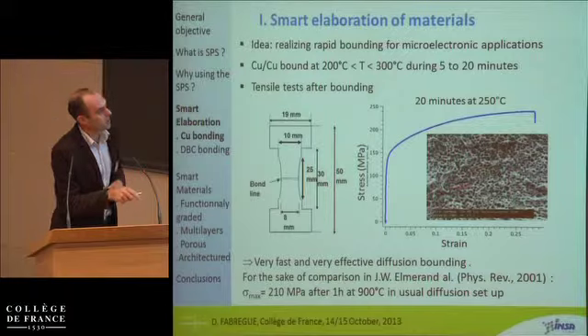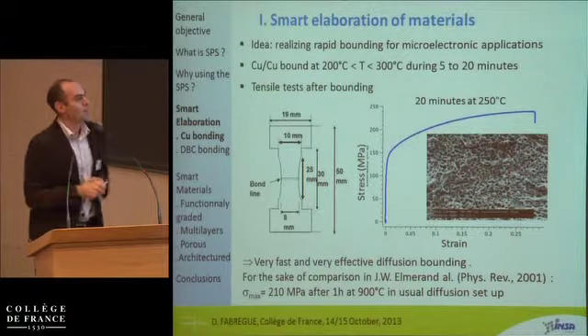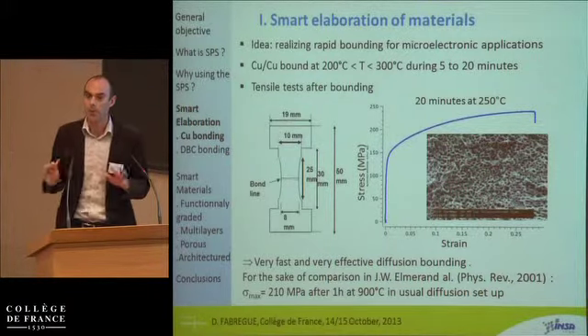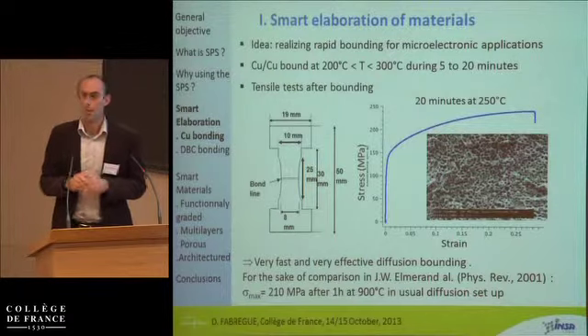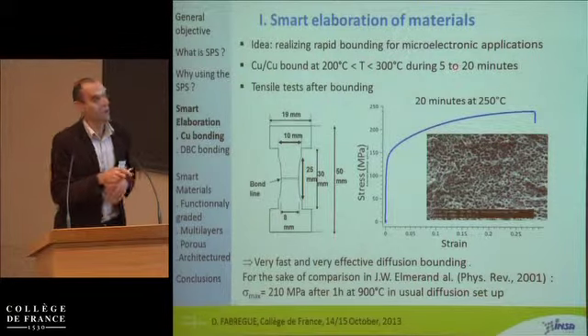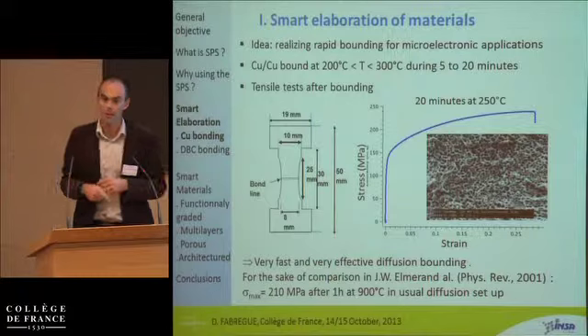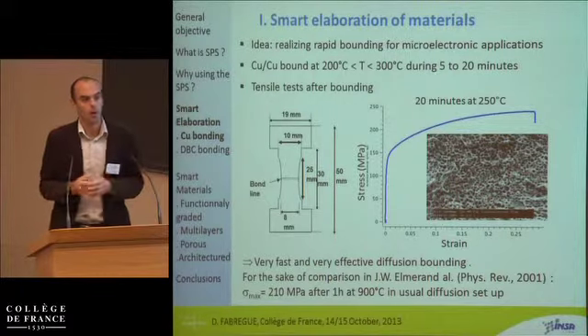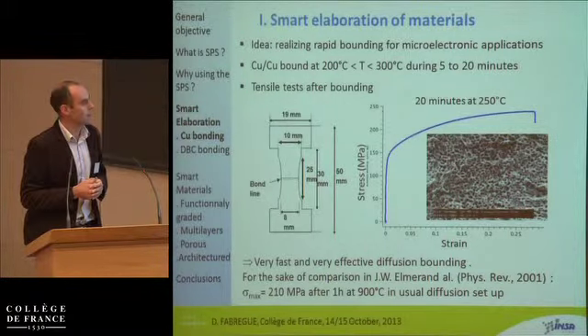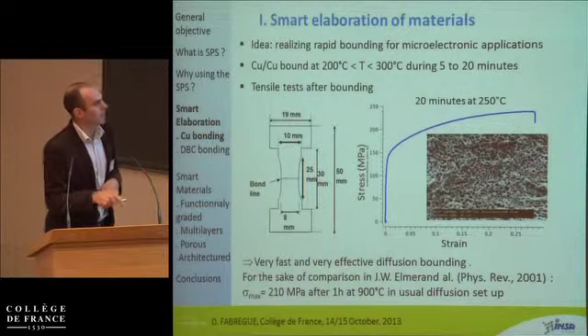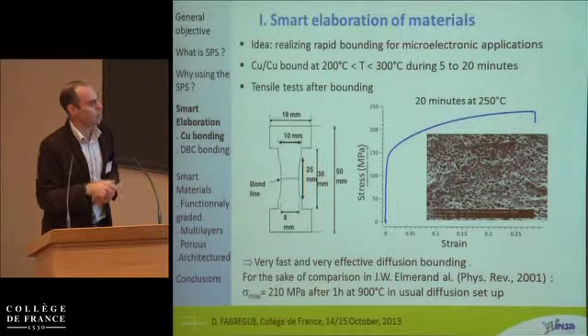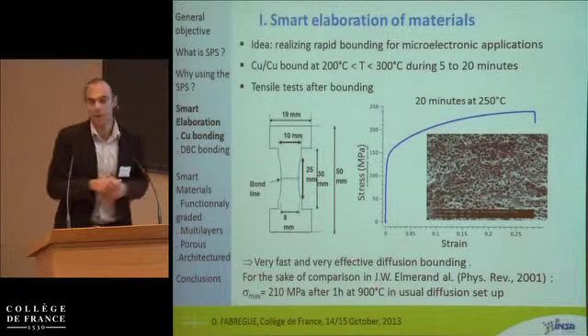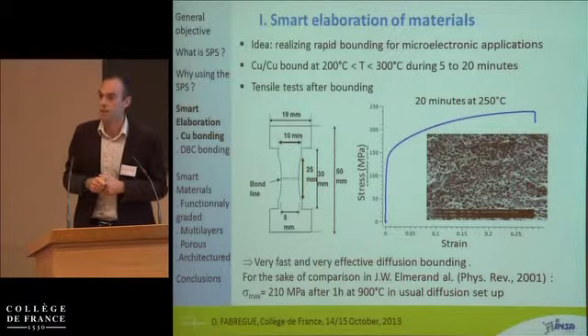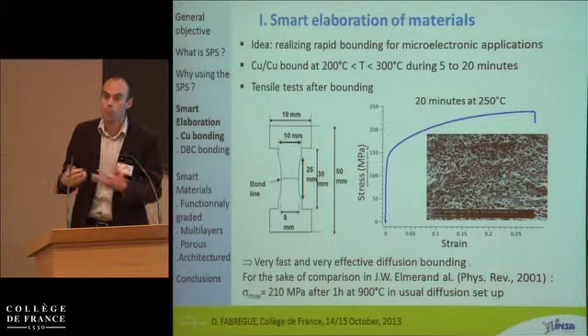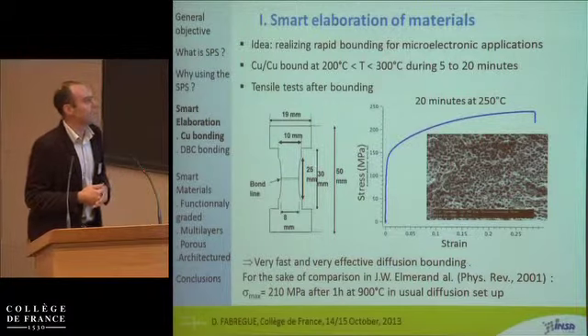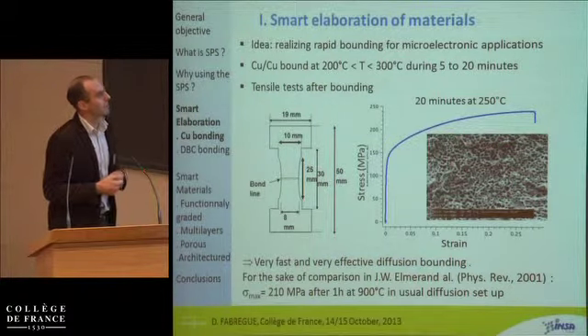If you look at the fracture surface, this is really ductile, and so that means that we erased the bonding line. Even for this very short time and very low temperature, it's exactly like there is no interface anymore. If you look at the literature, in order to get almost the same results, these people put an hour at 900 degrees C. So once again, this is proof of the accelerated diffusion process.